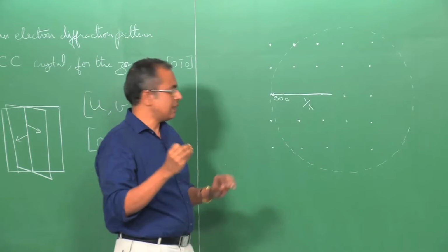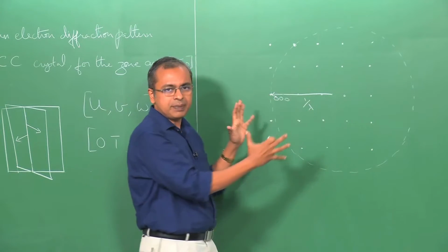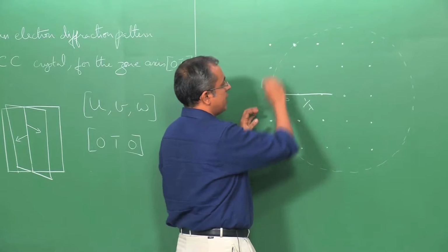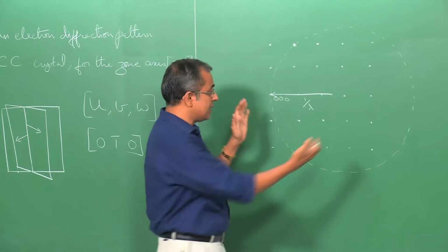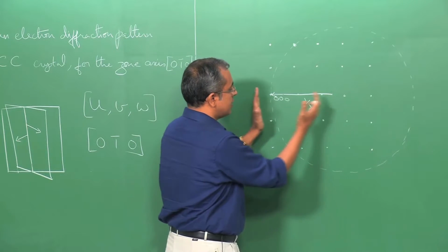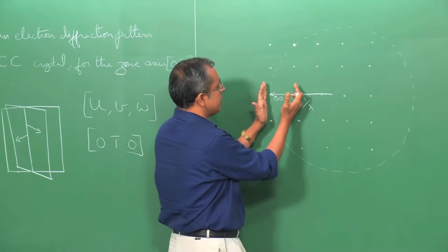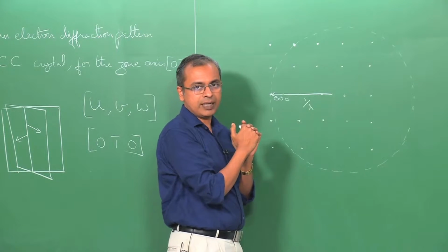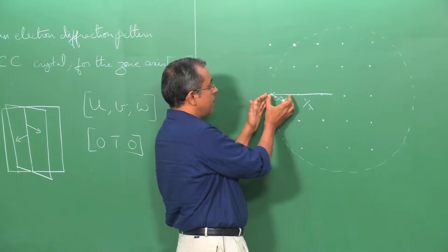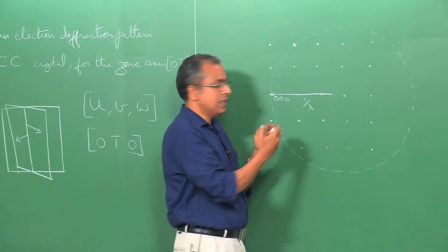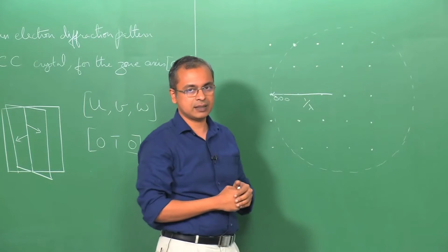But there is sort of an extreme end of this basic concept that I have shown you: you can have a small circle, a larger circle, an even larger circle and so on, based on the wavelength. And it is sort of an inverse picture, because the larger the wavelength that you are putting incident on the sample, the smaller is its reciprocal quantity. So, this 1 by lambda becomes smaller and smaller as your actual lambda goes up. The opposite happens as you keep decreasing the wavelength. The radius of this circle keeps becoming larger and larger.